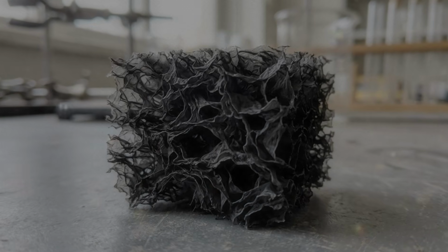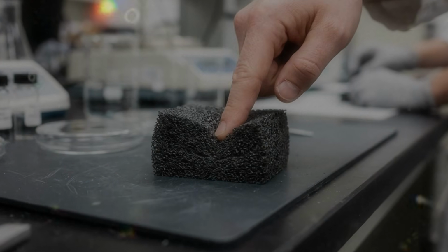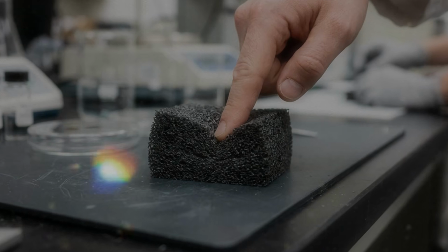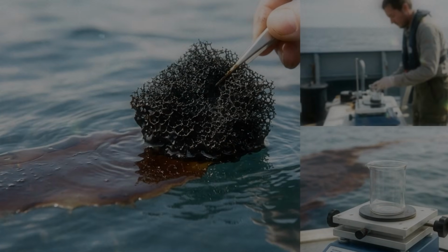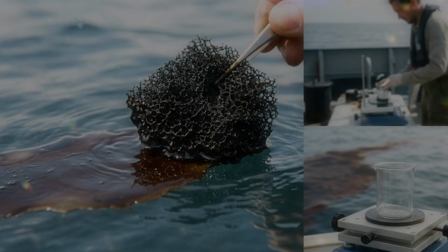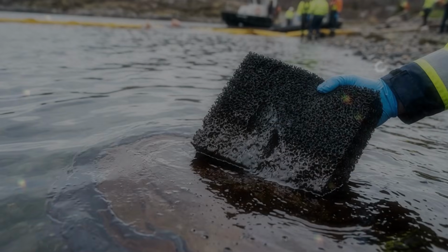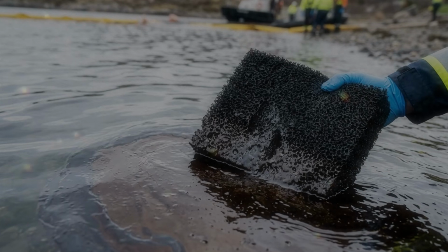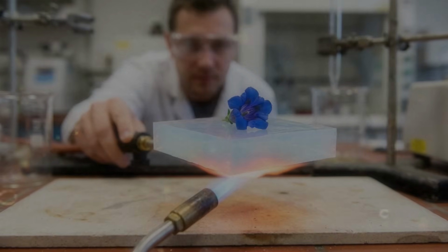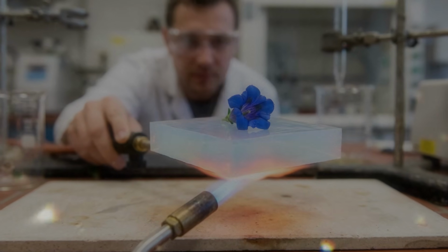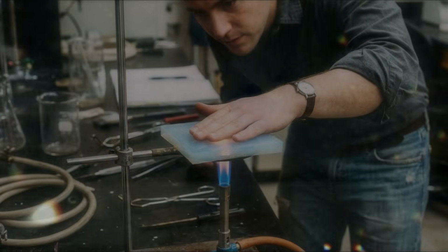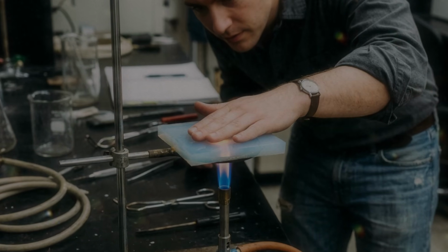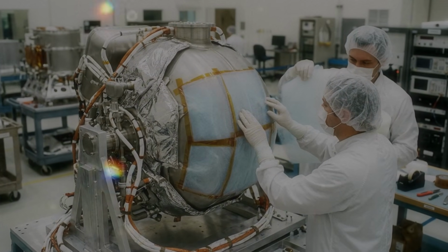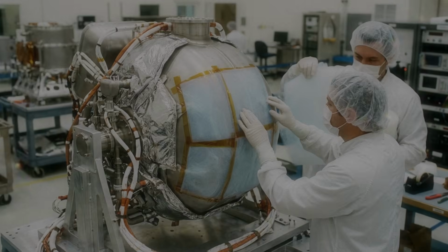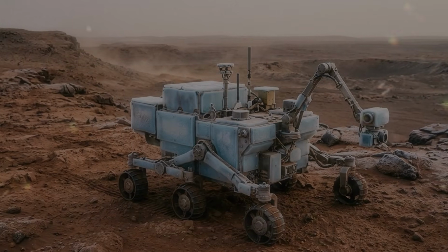Aerogel cleanup may prove most practical in smaller industrial spills, workshops, chemical plants, or controlled water treatment systems where the material can be contained and recovered. It could also serve in reusable filters that continuously separate oil from water. The same principle can collect organic solvents after a leak. A porous carbon material can draw in the solvent while remaining on the surface of water. The liquid can then be removed from the aerogel and treated separately. These applications reveal a useful difference between silica aerogel and aerographene. Silica aerogel is most established where heat must be controlled. Aerographene is attractive where heat, electricity, pressure, and chemical absorption must be combined.